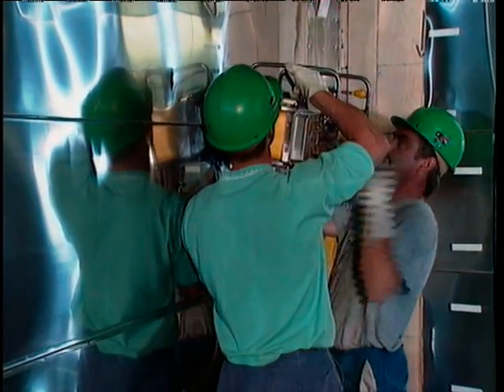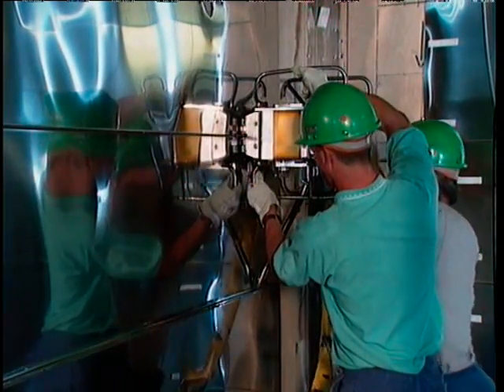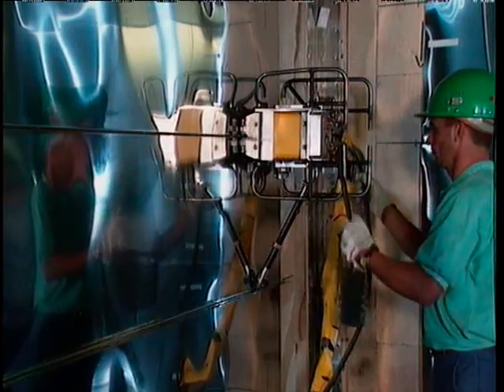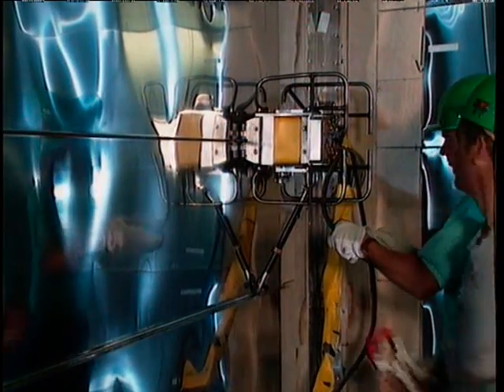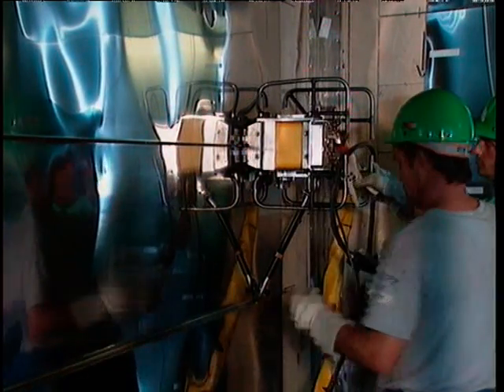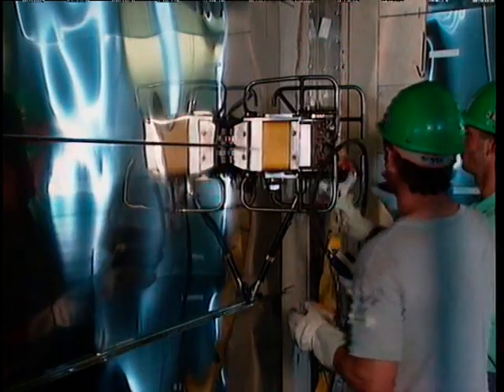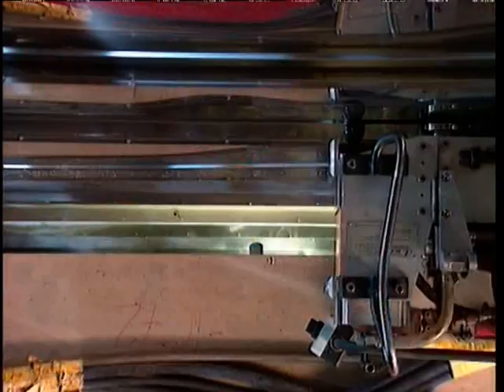The tightness welding is then carried out by fully automatic resistance seam welding. This is done on a continuous basis all along the length of the strake. The machine progresses along the strake at a speed of 1.5 meters per minute, held onto the rail which is formed by the emerging part of the tongue.